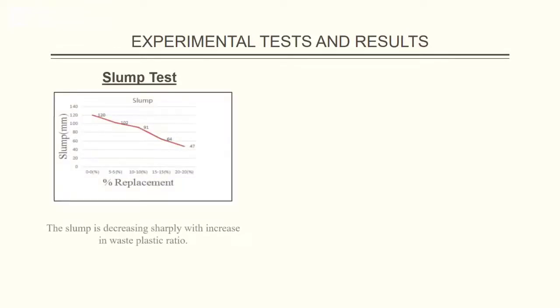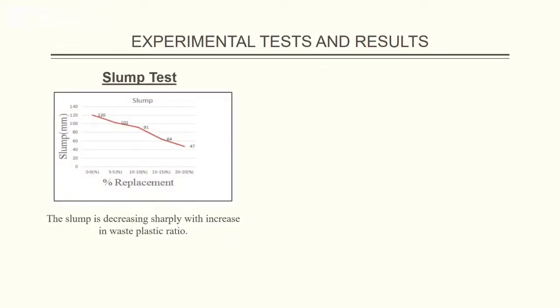Some of the experimental tests and results are: slump test. This test measures the consistency of fresh concrete before it sets. It is performed to check the workability of freshly made concrete. When this test was conducted, the slump decreased sharply with increase in waste plastic ratio. The reduced slump values of waste plastic concrete mix are due to slighter fluidity and non-uniformity in shape of plastic particles.